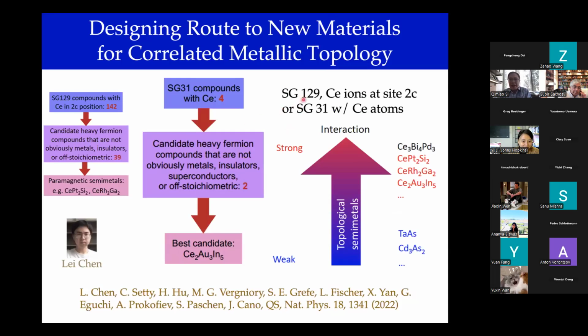We can look at, say, instead of the diamond lattice, some particular space groups, and use a database to identify cerium-based materials. So, for example, in this particular space group, we identify 142 of these. We use some intuition to screen down to a smaller number. In the end, we want the semi-metal. We want it to be strongly correlated, and instead of good insulators, good metals, and then to check measurements in the literature to see whether they are indeed strongly correlated, whether they are indeed semi-metallic. That leads to, in the end, 3 candidate materials.